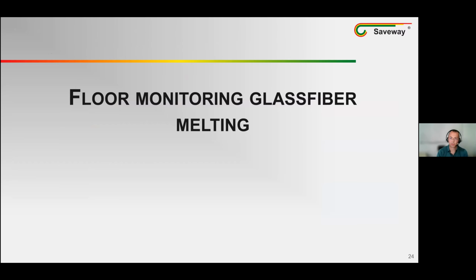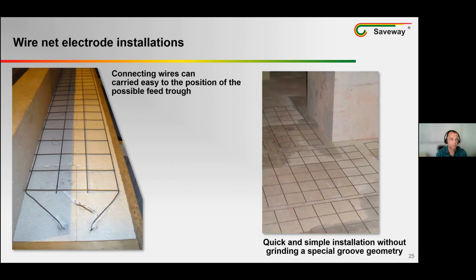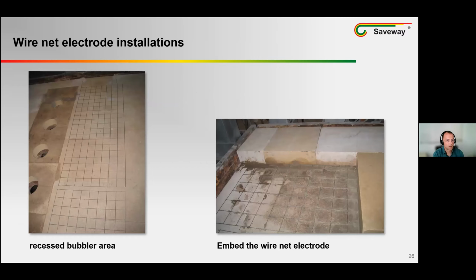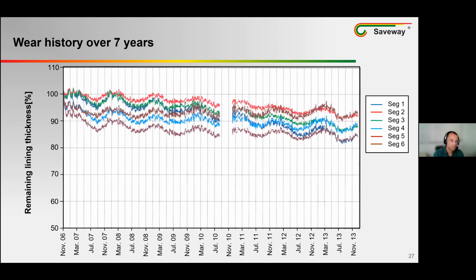Another application is the floor monitoring for glass fiber melting. On the left side, you can see the prefabricated sensor mat and transport packaging. Connecting wires can be carried out easily to the position of the possible feed-through. This installation is quick and simple without grinding a special groove geometry. The net electrode installation will avoid the bubbler area here too. We can see from this table that the remaining wall thickness gradually decreases with time over 7 years.